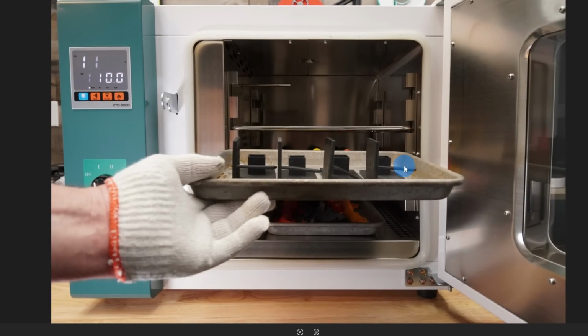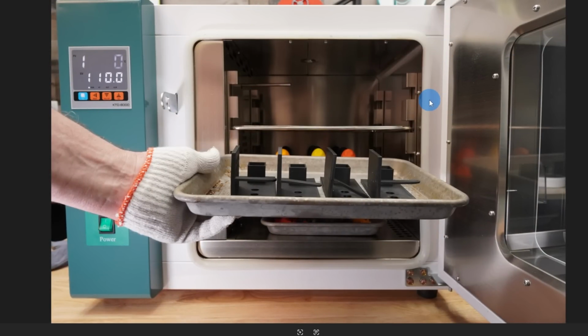110 degrees on the artifacts. Not much has changed. The COPE is now sagging. The PC Max is now sagging. The Silk PLA has already dropped all the way down, and the wall's starting to tip over. The Polyterra is starting to sag, but everything else is holding on. The High Temp PLA is holding on perfect. So I let it set for 2 hours at 110 degrees to see if anything changed. And really no change. It looks pretty much the same.